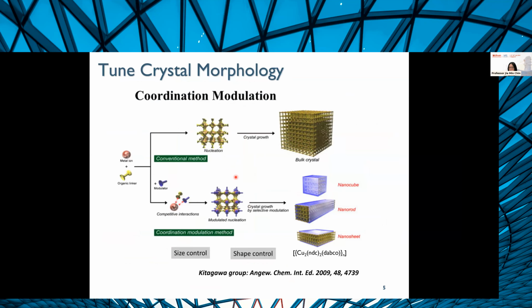And quite a while ago, in 2009, the Kitagawa group showed that they took this copper naphthalene dicarboxylate DABCO-based MOF, and they grew this material in the presence of a modulator. So in the conventional method of growing metal organic frameworks, you usually have your metal source, your organic linker, and then you react it, and you let these crystals nucleate, and then they slowly grow into bulk crystals.